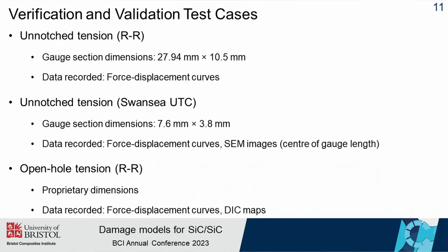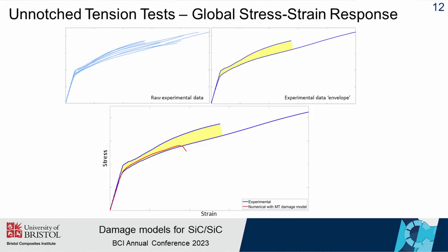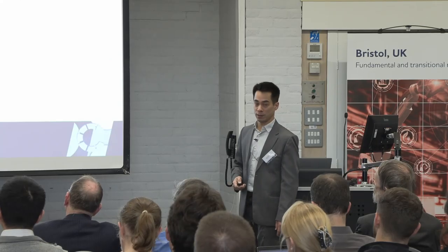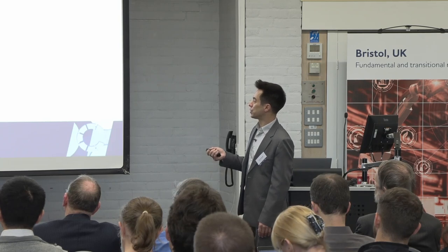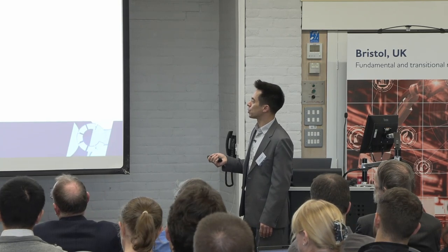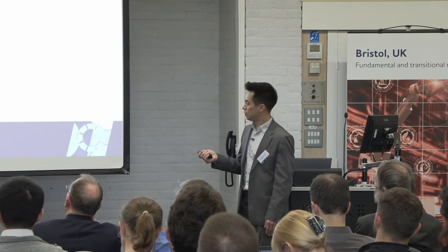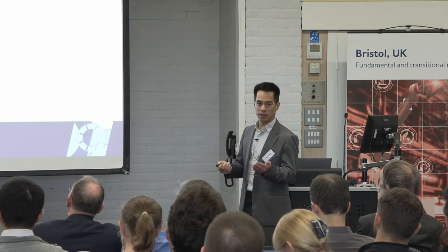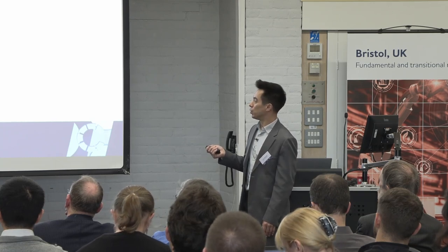So now a series of results conducted by both our industrial partners and also the wider UTC network, starting from a unnotched uniaxial tension test. So these are a bunch of experimental curves. We can extract some sort of envelope from those results and compare our models against these experimental data. What we can see is a very good representation of the behavior up to a certain level of strain, and then somehow a slightly premature failure of the models compared to the experiments.